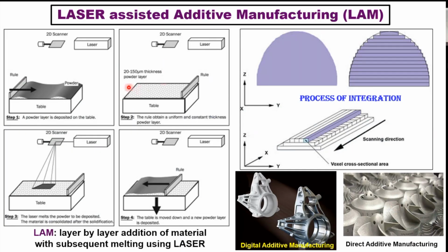So in a typical powder-based approach, one would like to possibly fill a tank with a certain volume of powder, then use a certain leveler to make the surface flat and smooth. The powder size can vary from micrometers to millimeters even. And you can also mix different types of powders, but the bed has to be a sort of compacted bed. And then when you have a laser shining over the particular powder bed, then you melt only a certain directed region and not the rest. And you move either the beam or the bed, whichever is suitable, on the table, and then end up with a particular shape. And when you build that shape, we have to realize that you build layer by layer.